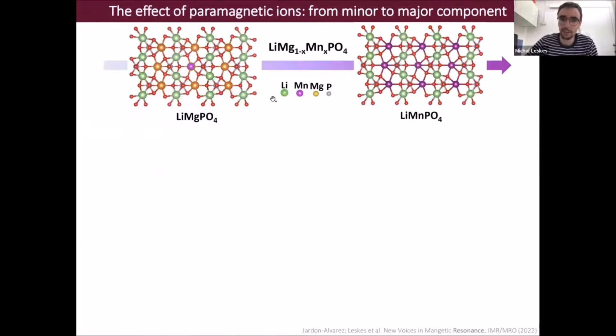So the initial question that I asked before was, how does the concentration of paramagnetic species affect our NMR signal? And to answer this question, we prepared a series of samples. Based on this chemical structure, this lithium magnesium manganese phosphate, we replaced the diamagnetic magnesium with manganese. And the nice thing about this structure is that we can do this from 0% to 100% without changing the crystal structure of the material.